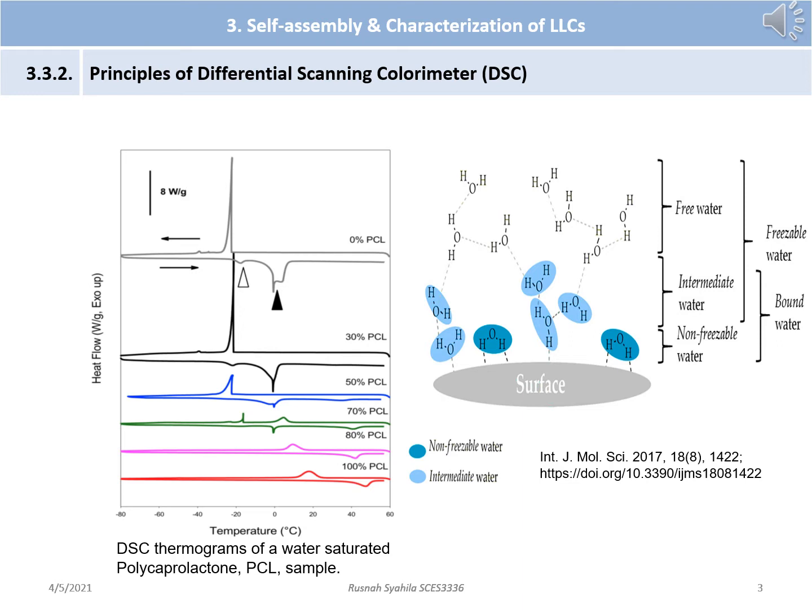Melting temperature of freezable bound water is usually lower than bulk water due to hydrogen bonding, but changes slightly or remains constant with different ratios of sample and water mixtures. In some cases, a cold crystallization peak appears on the heating cycle for an intermediate water concentration range. That is mainly due to some water molecules being unable to crystallize completely, yielding a higher fraction of water molecules that are non-freezable under the experimental condition.